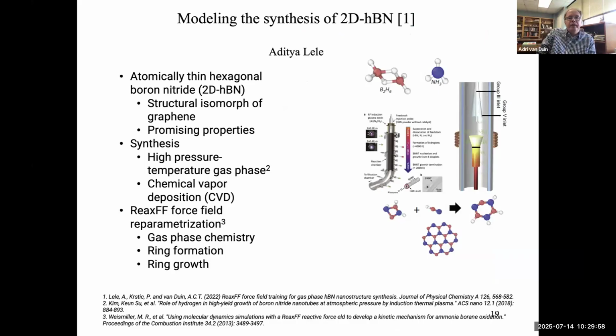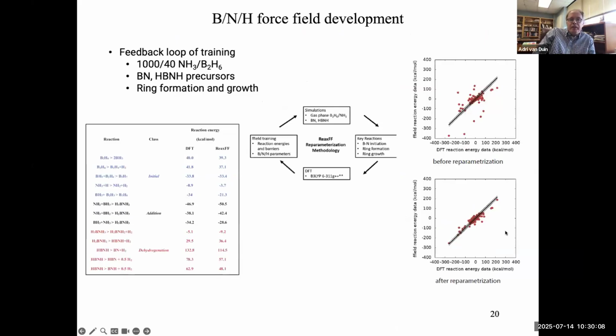Changing to a new material for a second. Boron nitride is clearly very isomorphous to graphitic materials. So we have been looking at how to grow these with ReaxFF. We have a kind of self-training process going on. We first train the force field against a couple of sensible reactions. Then we do some high temperature simulations with that force field. We generate a large amount of low molecular weight species.